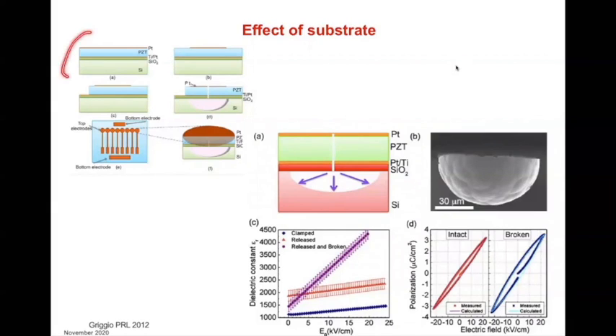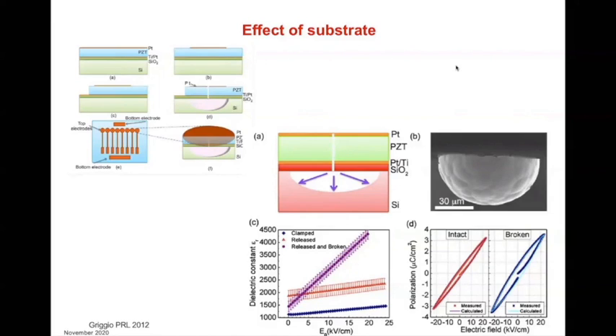There are other tricks you can do. If you consider this case, the blue is the active film and this is the substrate, which can be much thicker — typical substrate values are 300 microns and the film is 100 nanometers to one micron. However, what you can do is make a hole below the film using etching, so that the film is partially released, there is less pressure from the substrate on the film, and you can have much more movement and deformation.